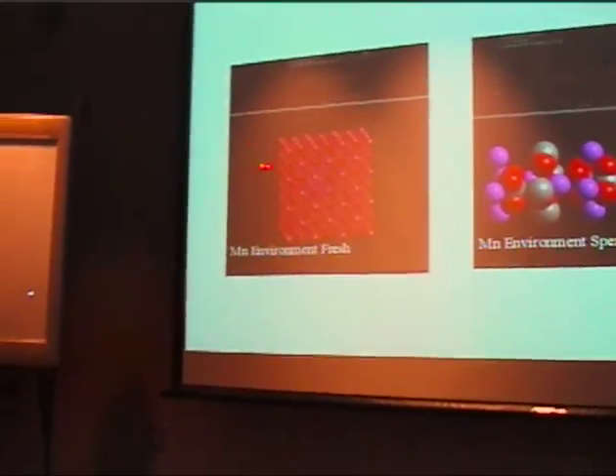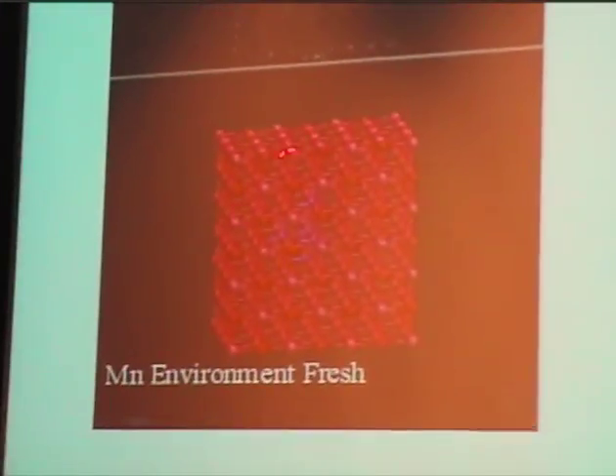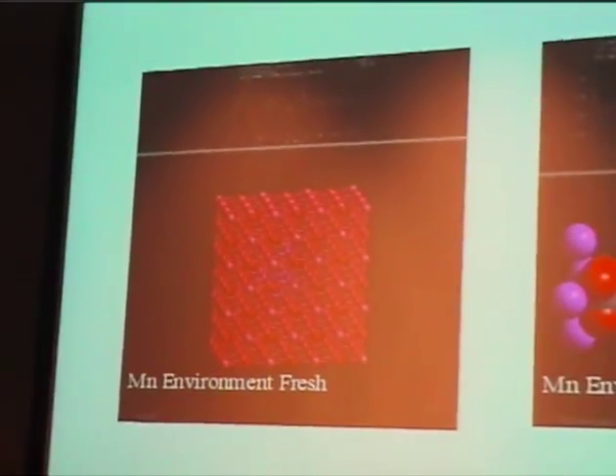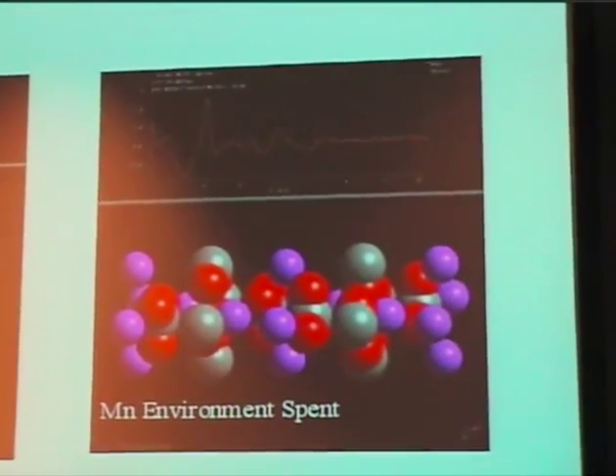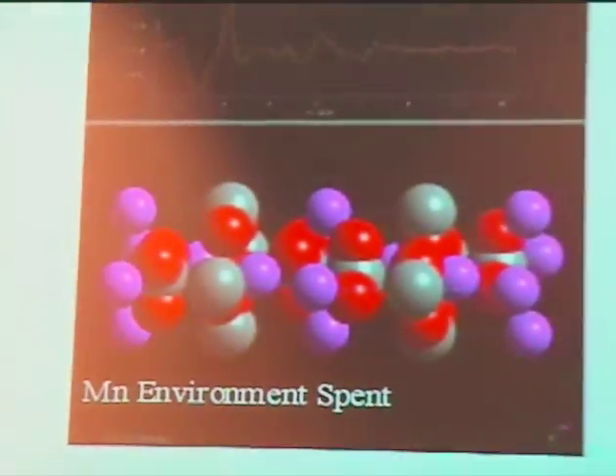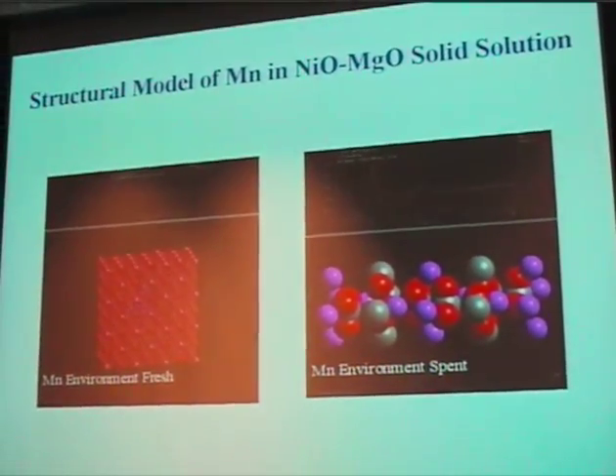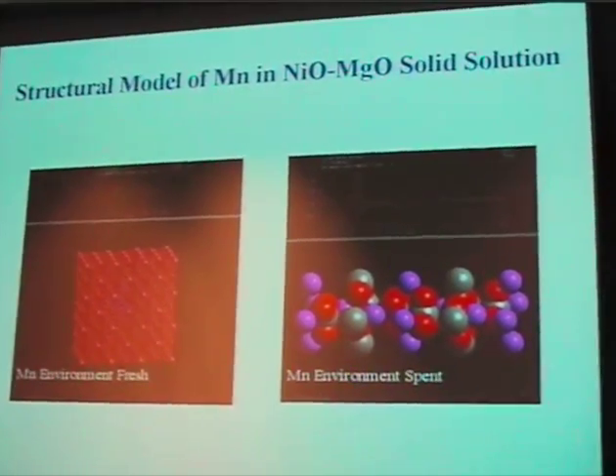And just using molecular modeling, we had a program called Sirius. We're interested to see how the manganese would be distributed within the NiO-MgO solid solution, fairly evenly distributed, whereas after use, it would support the fact that perhaps you could be forming a manganese oxycarbide and that it would move up to the surface of the catalyst. So a lot of this would be an interesting problem to pursue further. In other words, why is it that the manganese helps to maintain the catalyst, keep the nickel reduced, and minimize coke?